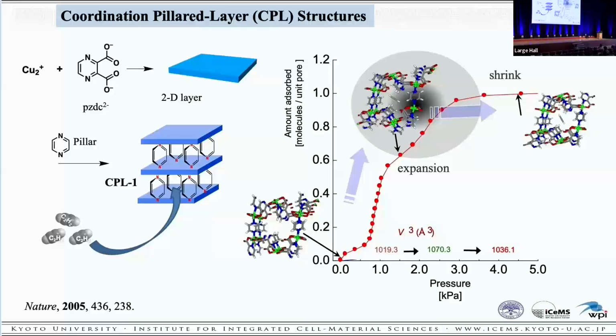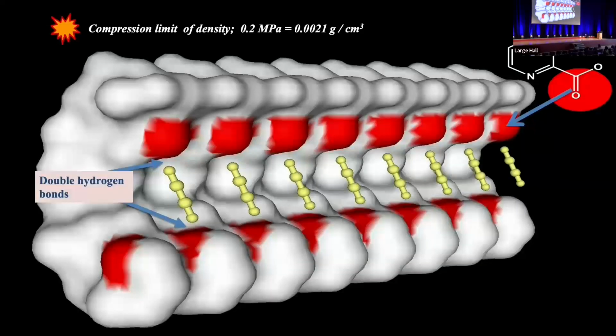This is the adsorption isotherm for acetylene, showing the 2 steps. Structural analysis reveals that this MOF compound, CPL-1, initially expands and then contracts. The framework of the MOF is flexible for gas adsorption. This shows a cross-section of a single channel in which acetylene is incorporated. The acetylene molecules are aligned regularly in a single row.